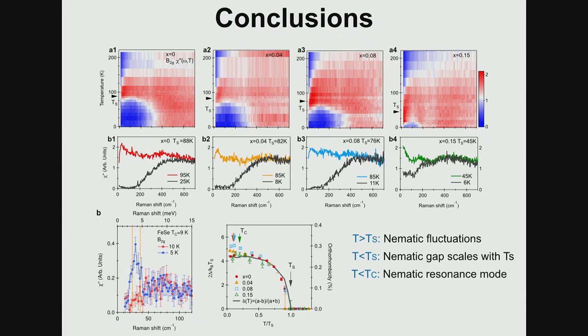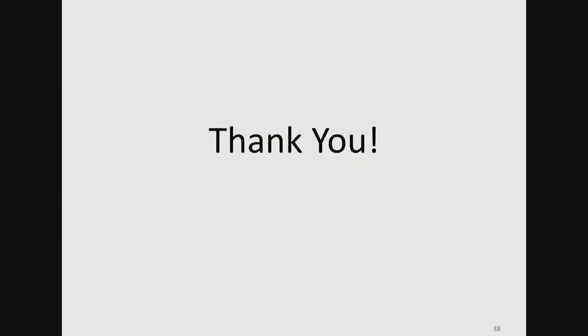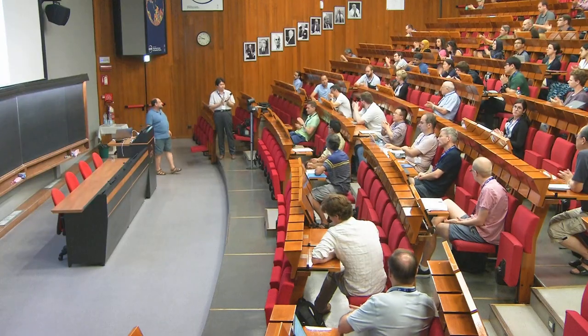What really happens below superconducting transition—this is now pristine sample—in the gap develops a collective mode, not very strong because all the signals here are very low, but there is definitely a collective mode. And now this mode, unlike in that data I showed for sodium 111, arises in the superconducting state with broken C4 symmetry in C2 state. So it must have an amplitude mode origin, which again can couple now—that's for you, Laura—couple to superconducting amplitude mode, and interesting things can come out from that. Okay, so I'm done and I'll take the questions. Thank you. Thank you very much. Good questions.